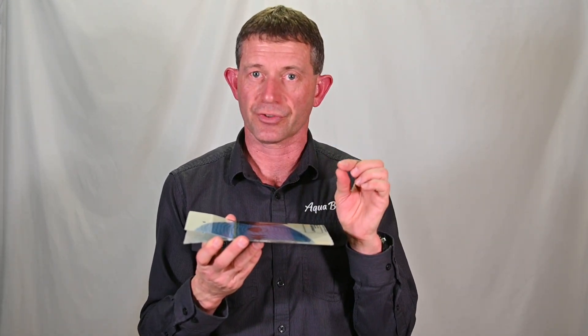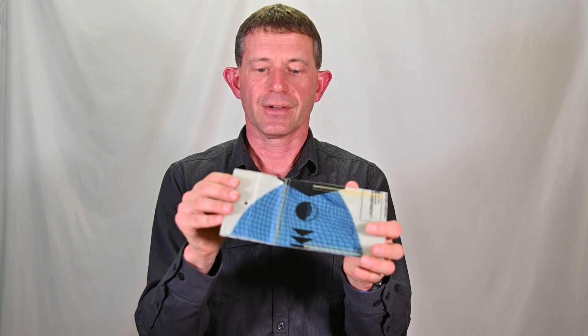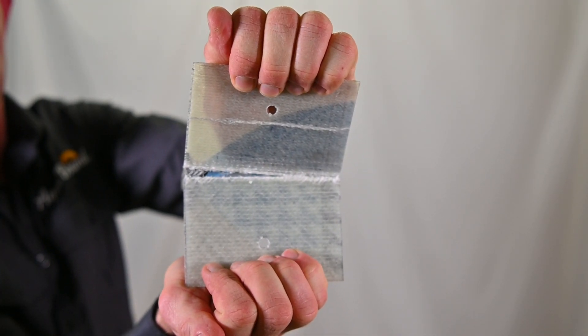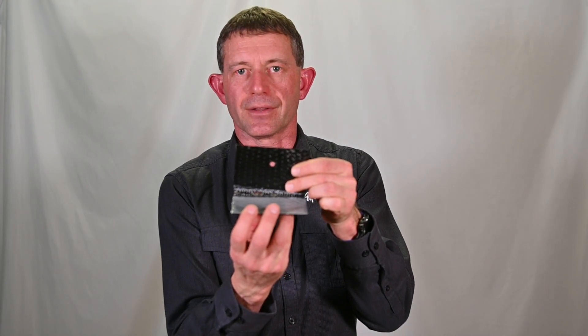Multiple composite blades have multiple layers of fiberglass — the samples shown previously were just two layers. This is the actual layup of our Aerial blade, which has multiple layers of fiberglass stitched together with multiple stitches. Under the same testing scenario, the force required to break those fibers increased significantly, and again the stitching did not break. Whether it's a carbon or fiberglass blade, the failure mode is the same. The carbon version of our Aerial blade showed resistance to delamination up to 500 pounds. We go from 18 pounds on standard product to almost 500 pounds with Lamlock — which is why we're so excited about this patent-pending technology.